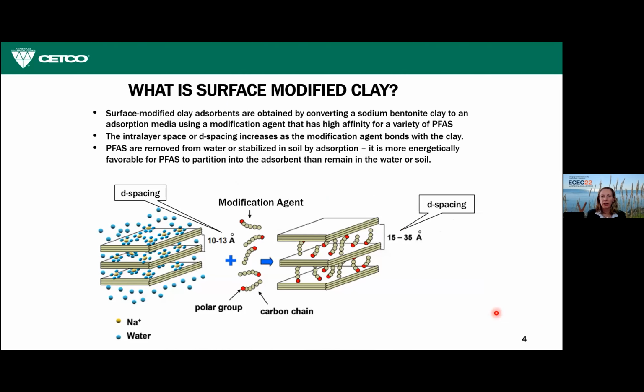Okay, so what is surface modified clay? Surface modified clay adsorbents are obtained by converting sodium bentonite to an adsorption media using a modification agent that has a high affinity for a variety of PFAS. And basically that's what this picture here shows. So clay is these platelets or sheets of alumina and silica hydroxide with cations and water in between, and that gives the property that most people know about bentonite clay, which is that it swells when you put it in water, because water comes into these intergallery spaces and the clay swells.